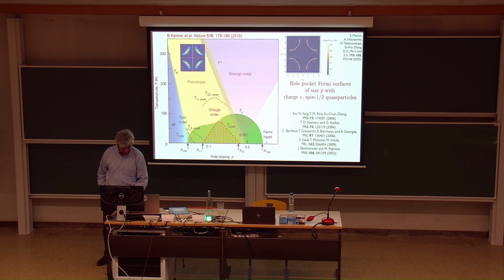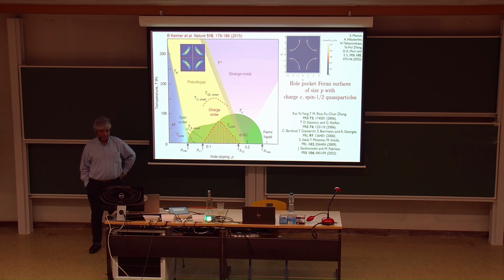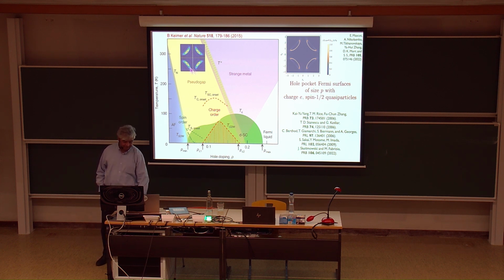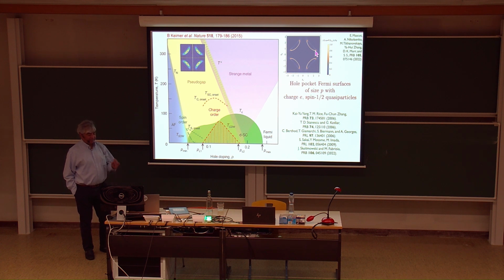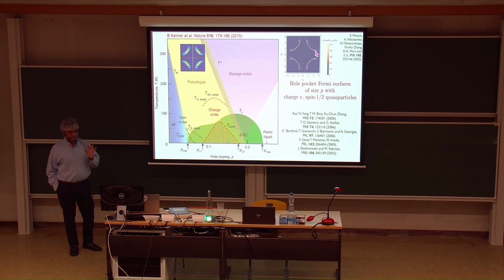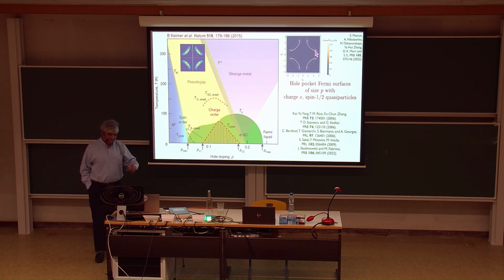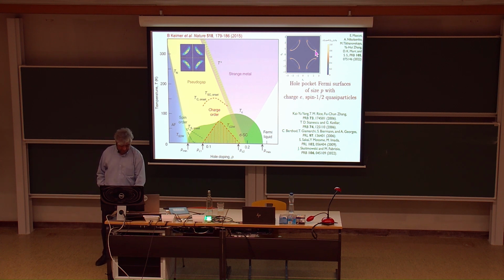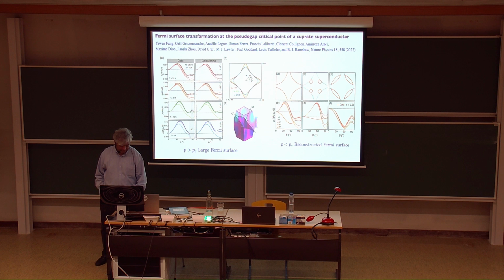All right. So let me tell you one thing about the theory of the pseudogap metal, which is actually a feature of many other works that I've cited here over the years. Our claim is that these Fermi arcs are really a remnant of actual pockets. There are actually whole pockets here with a backside. It's just that the intensity of photoemission is very weak at the back. So they're really pockets of size p, and these are pockets of just ordinary electrons, charge e, spin a half quasi-particles. And this is a feature of many other works. But one of the things we're going to emphasize, and really the key to special features of our work, is that once you have such pockets, then you've done something that's not allowed by the usual principles of condensed matter physics.